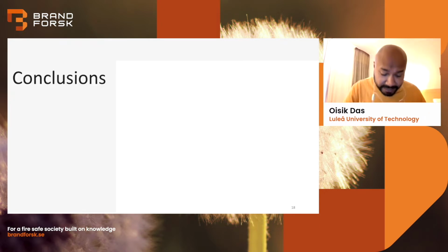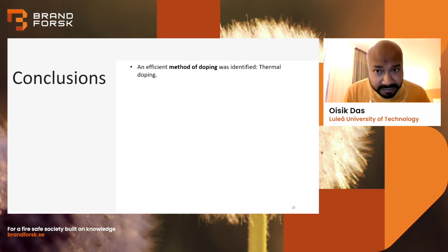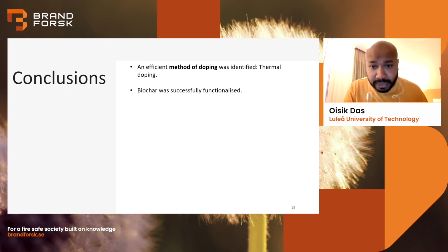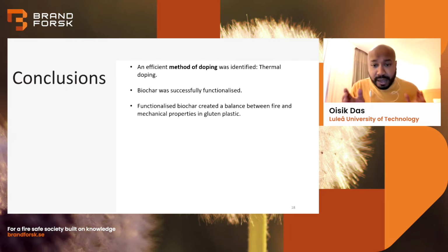So for the phase 1 part of the project, the conclusions are we have identified an efficient method of doping, which was thermal doping, because we have seen that it preserves mechanical strength, it increases activation energy, it has char structures which are more compact and rigid, and it has a peak heat release rate which is the lowest amongst the tested samples. And we can thus conclude that the biochar was successfully functionalized with the fire retardant, and we have been able to create a balance between the fire and mechanical properties in gluten plastic.